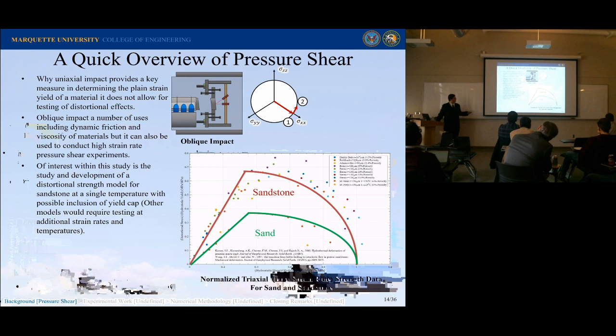Quick overview of pressure shear. Why do we want to do it? So typical uniaxial experiments will just load us in one principal stress area, but pressure shear takes us off that axis and gives us a little bit better of a yield surface, if you remember the Drucker-Prager. In order to do these, we use the oblique impact experiment. It has a number of uses: dynamic friction, viscosity of materials, but we're going to use it for pressure shear experiments. So of interest in this study is the distortional strength model of sandstone.